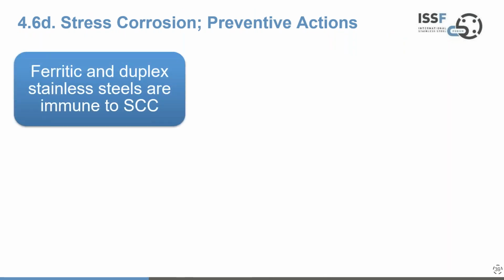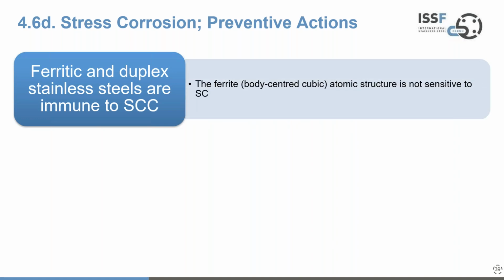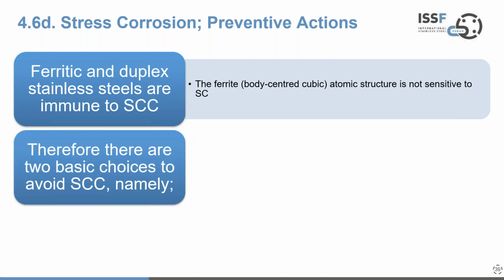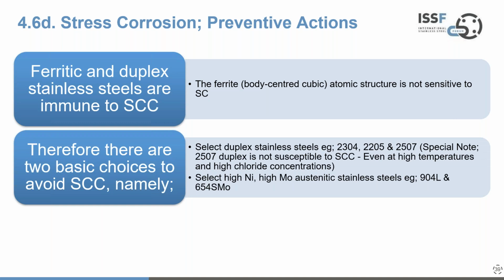So the preventive actions. Ferritic and duplex stainless steels are pretty much immune to stress corrosion cracking, noting that there are some environment concentration and some temperature effects as you move to the sort of leaner duplex steels. And this is because the ferritic atomic structure, the body-centered cubic structure, is not sensitive to this stress corrosion phenomenon. So you're left with two basic choices. Select duplex stainless steels, recognizing that there's a different degree of susceptibility, even though they are much less susceptible than other products, or select high nickel, high molybdenum austenitic stainlesses like the 904L or 654 SMO types, highly alloyed austenitic grades.